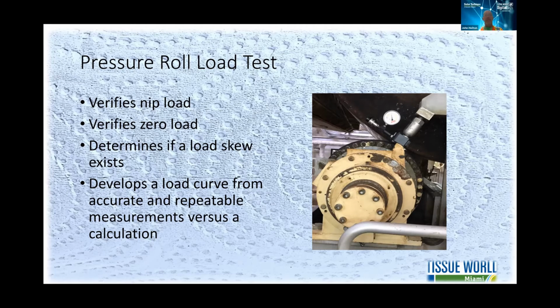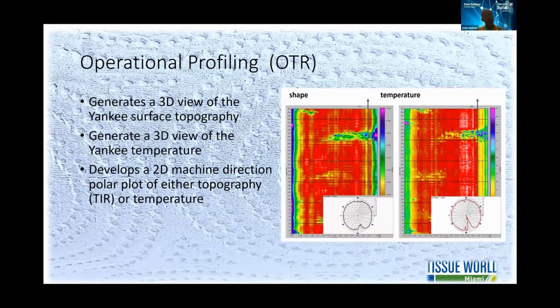Operational profiling, and this is a lot of different subject matter will go into this, but operational profiling, often known in the industry as OTR, generates a 3D view of the Yankee surface topography. It generates a 3D view of the Yankee surface temperature and develops a 2D view machine direction polar plot of either the topography or the temperature. And you can see here in the lower corner, this would be the polar plot generated from a single line of data, whether it be topography or temperature.